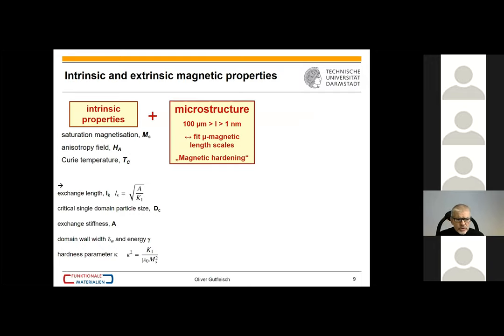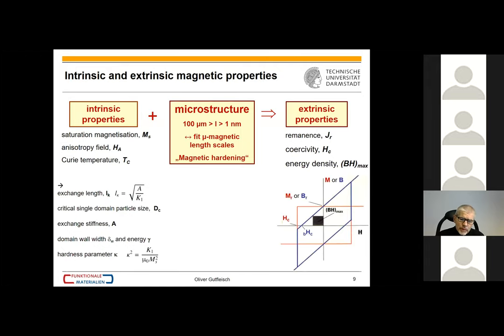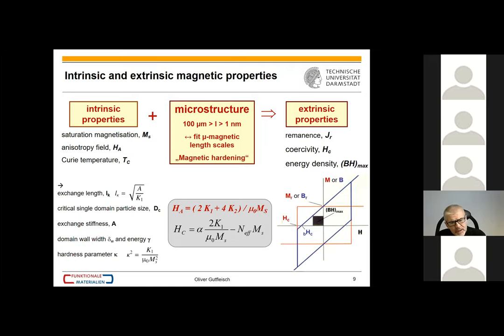And so just as a quick reminder for permanent magnets, but of course true for almost all magnetic materials, we have our intrinsic parameters, we have the characteristic micromagnetic length scales, and then we need to understand how these micromagnetic length scales crosstalk or couple with our microstructure, so that at the end we get our extrinsic properties, our hysteresis loop. And by the way, especially for permanent magnets, it is very interesting that we need to solve this Brown paradox, which is the huge discrepancy between the anisotropy field and the coercivity. And that is one of the challenges we are basically taking on.